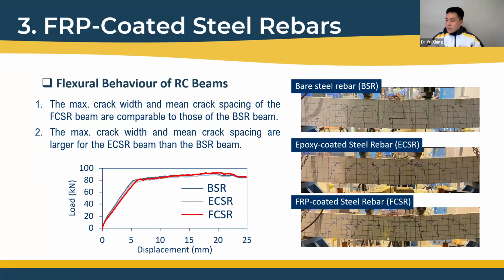We then used 3 types of rebars to make concrete beams for flexural loading. The load displacement curves are generally similar. But the ultimate load for the beam reinforced with FRP coated steel rebar was slightly higher than the other two beams, though generally very close.